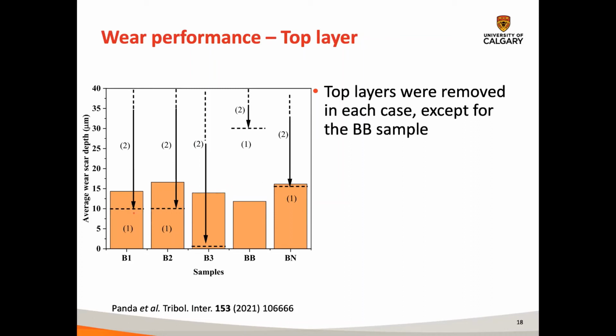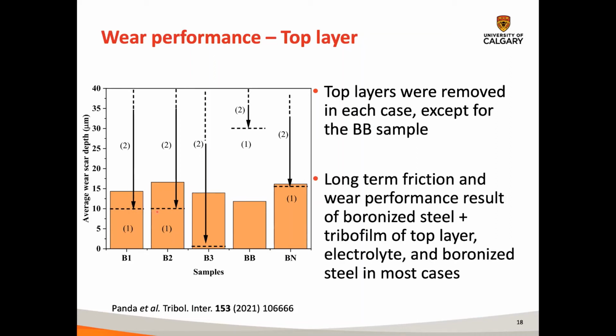In the other cases of these boronized steels, the top layer was completely removed, and we were wearing out the boronized FeB, Fe2B coatings. Okay, and so this really shows that this enhanced boronized top layer would be important to use if you wanted to ensure that you had this lubricious top layer. What we'll show later is that the long-term friction performance is really dictated by the tribofilm, or the chemistry of the worn material, the electrolyte, and the boronized steel below it.